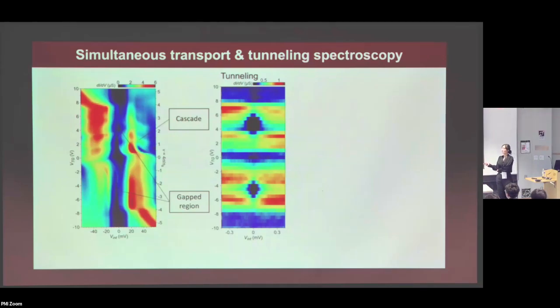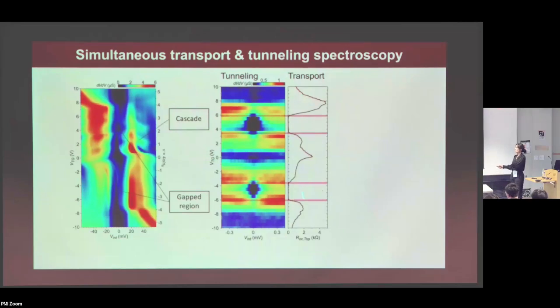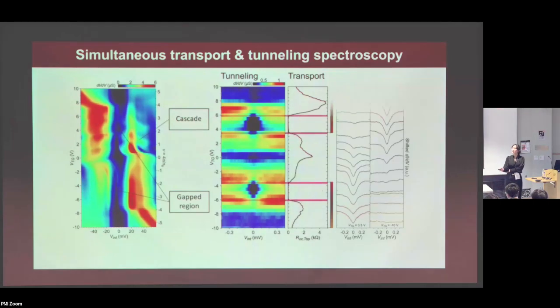So finally, we can make use of the fact that we can do simultaneous transport in the same exact device. We can plot the transport resistance in this scale across exactly the same doping, and then you can see that these two regions correspond exactly to the zero resistance regions in transport, which correspond to the superconducting state. And you can also take line cuts in these tunneling spectra and see that the development of these dips is happening exactly at these superconducting regions.